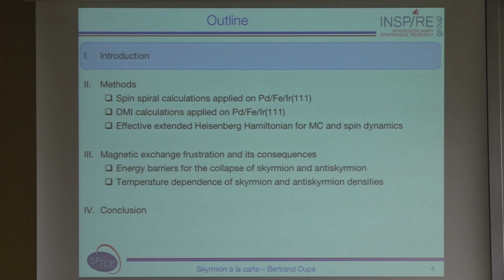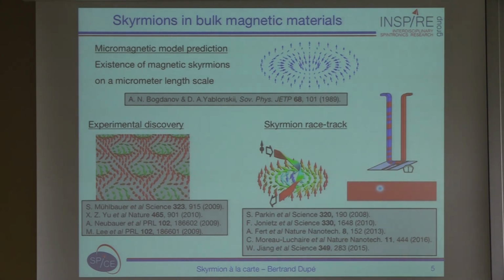So first, a very short introduction. You have seen already that Skyrmions are actually zero-dimensional objects. They were predicted first in this paper in 1989, the prediction that they might occur in materials. A skyrmion is composed of two things: a ferromagnetic background around, and a core of the skyrmion. The ferromagnetic background is pointing up, and the core is pointing down. As you go from the ferromagnetic background to the core, wherever you are, the magnetic moments are always rotating in the same direction. These objects are therefore called chiral.